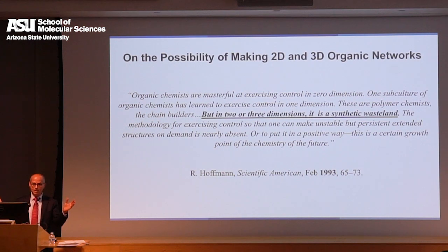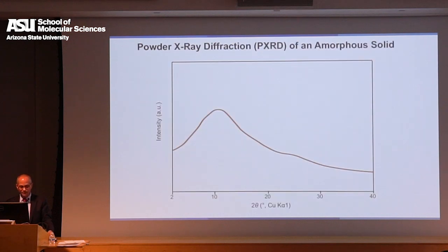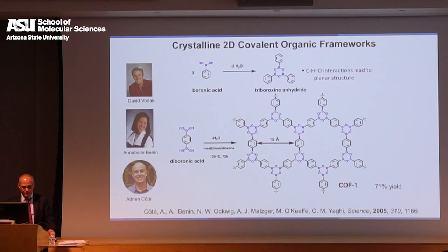So it was wide open. Nobody had managed to crystallize anything for organic compounds in two and three dimensions, because every time you did that, you got a powder diffraction that looks like this. And a chemist can't do very much with that. It's very poorly crystalline or amorphous. So what we did in my group, we were able to turn this into a true crystalline material. And that's from this reaction, taking this diboronic acid and dehydrating it. You would think this is a simple reaction, which it is, but it doesn't make crystalline material. So it took the students many years to get this to work.